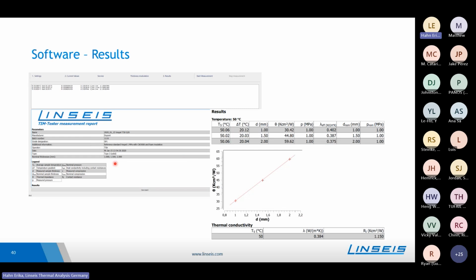It will show then the general information as well as the individual steps. So here you can see a test of our reference material performed at 50-degree sample temperature with 20-degree gradient over the sample. Thicknesses were 1, 1.5, and 2 millimeter with a contact pressure of 1 megapascal. And these are the thermal impedances determined during the test.